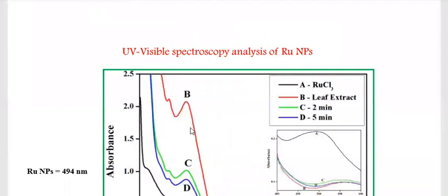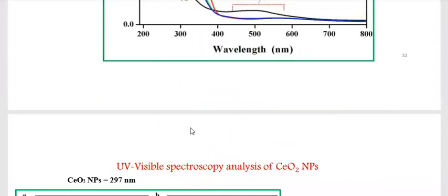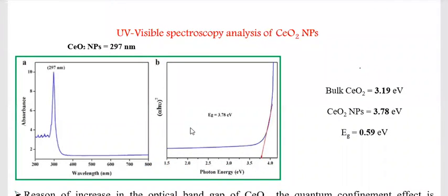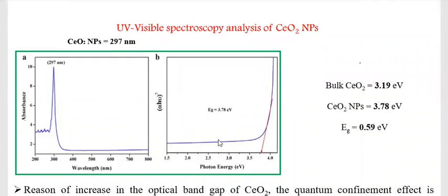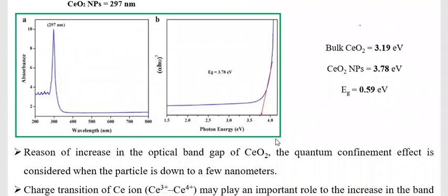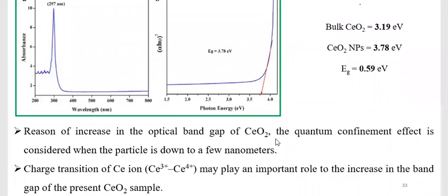Surface plasmon resonance of the nanoparticles. Silver nanoparticles show peaks at 428, 425, 538, and 550 nanometers, which is called collective electron charge oscillation in the metal nanoparticle excited by light. In a similar manner, the ruthenium nanoparticle has a lambda max of 494 nanometers, and the cerium oxide nanoparticles show 297 nanometers. The cerium oxide bulk material has 3.19 electron volts, and when synthesized as nanoparticles, 3.78.